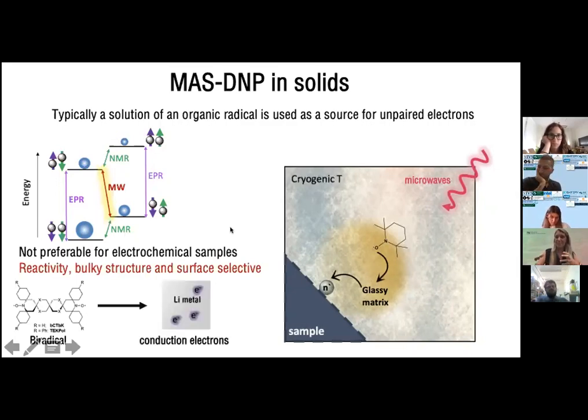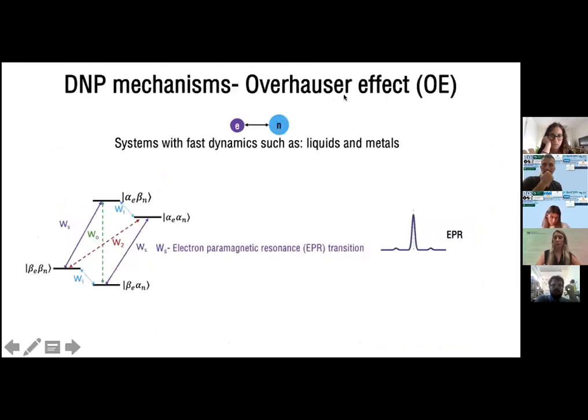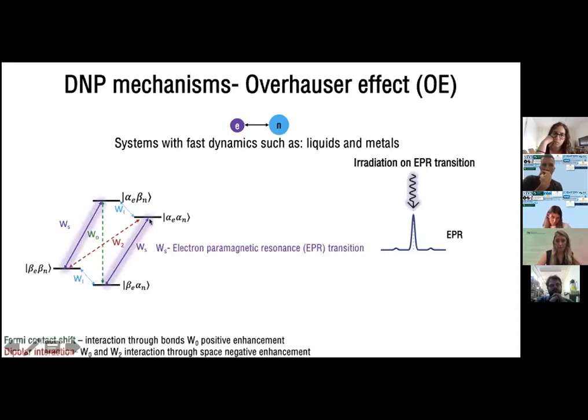We have internal spin polarization inside our batteries. We have the dendrites, which contain lithium metal inside them. We have the conduction electrons that we can use as unpaired electrons. And the mechanism that describes this is called the Overhauser mechanism. It's characteristic of systems with fast dynamics such as liquids and metals. You have one electron and one nucleus coupled between them. As you can see here, it can be described by a four energy level diagram. You continuously irradiate the EPR transition, the electron-electron transition, and it induces relaxation processes.